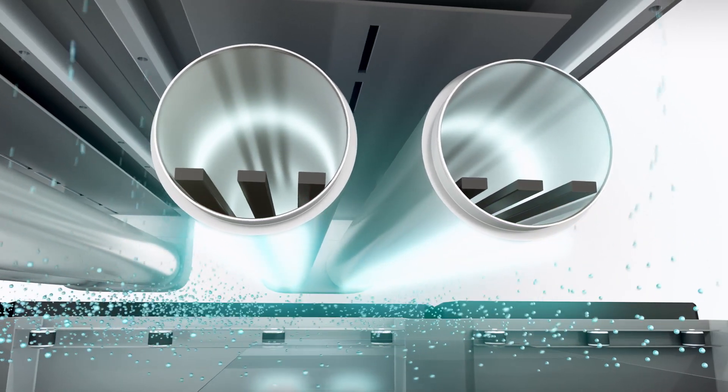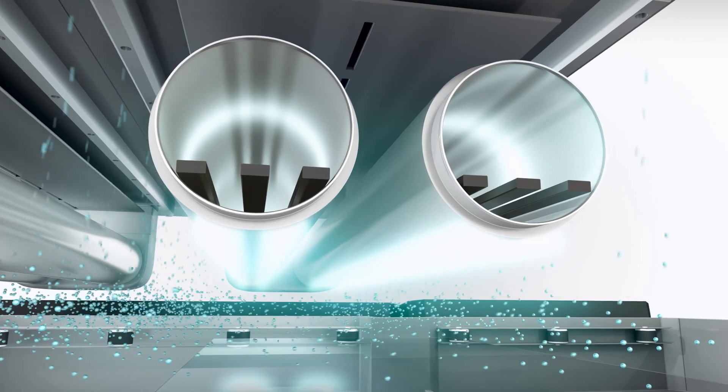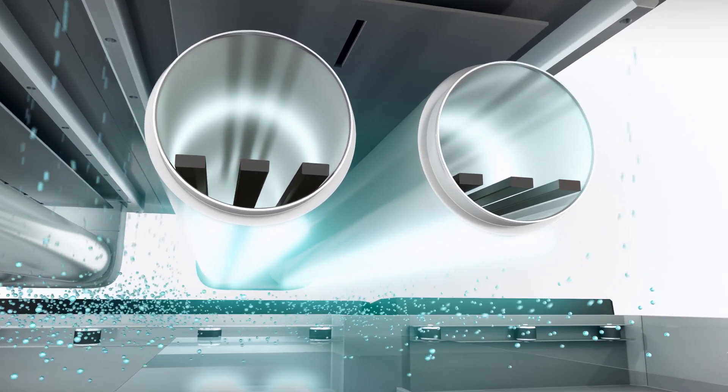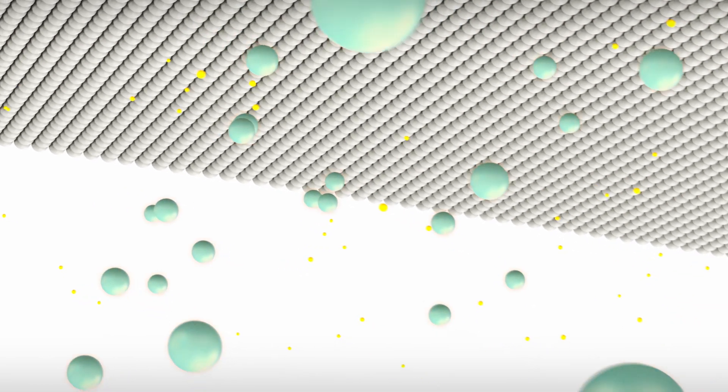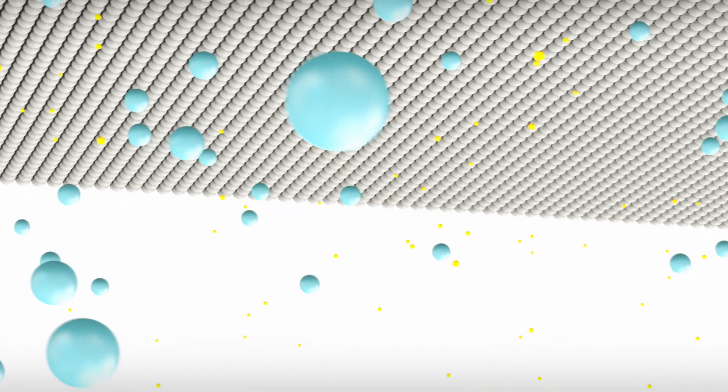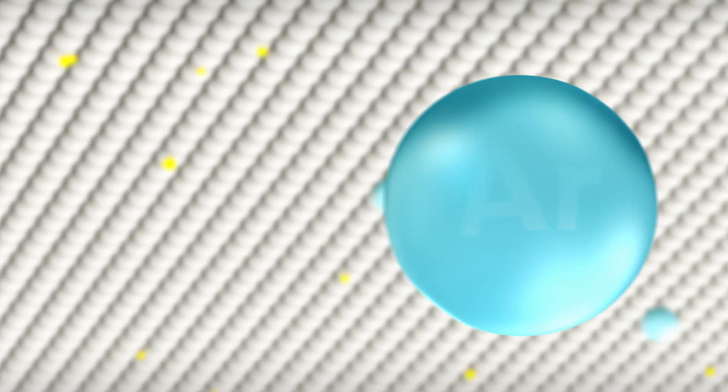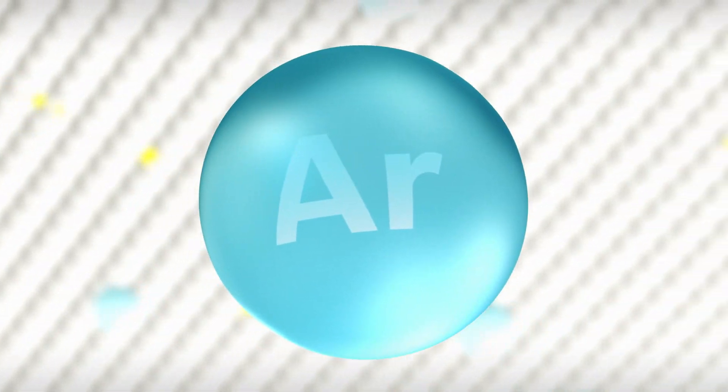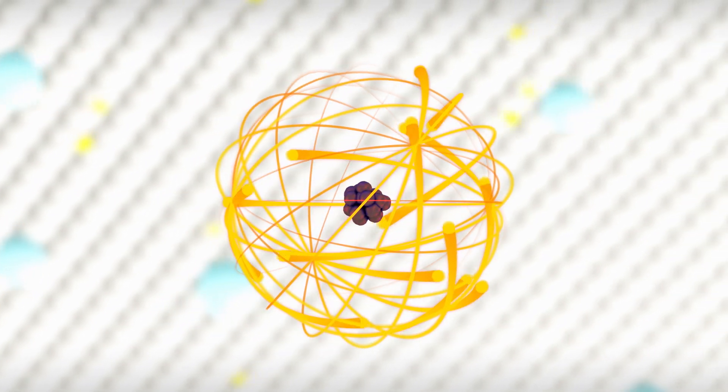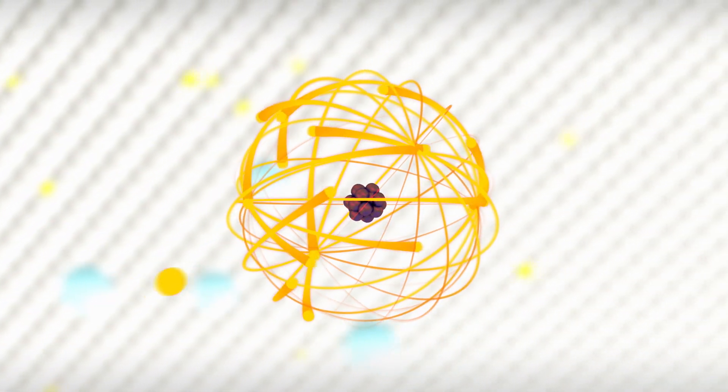A high voltage is applied to the molybdenum target and creates a plasma which is concentrated along the magnetic field. The plasma consists of argon atoms, positively charged argon ions, and free electrons. The positively charged argon ions are continuously generated by electrons hitting the argon atoms.